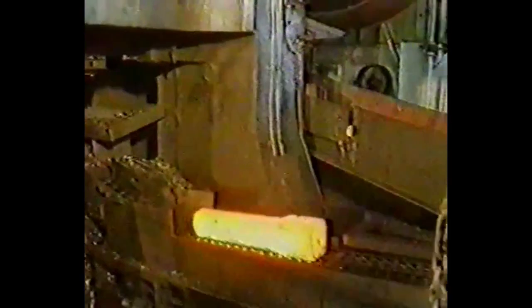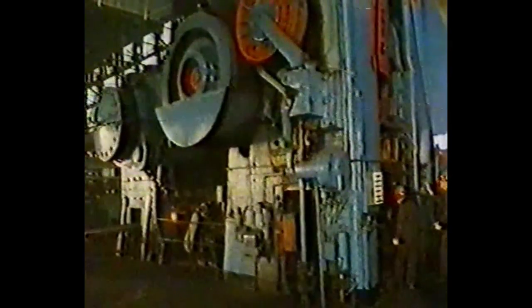Next, they go by conveyor to a pre-forming press, which rounds off the corners to prevent excessive wear on the die blocks. From here, they go to the press itself, which is capable of applying pressures up to 6,000 tons. It's one of the largest enclosed die presses in Europe. The pre-formed billet is first of all placed on the blocker impression and then onto the finisher impression. A pair of dies like this could produce up to 8,000 components before they wear out.